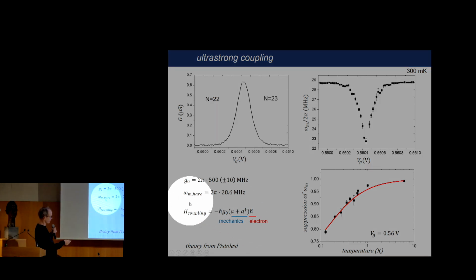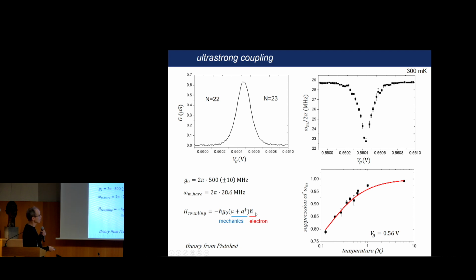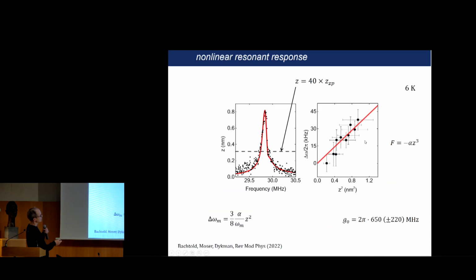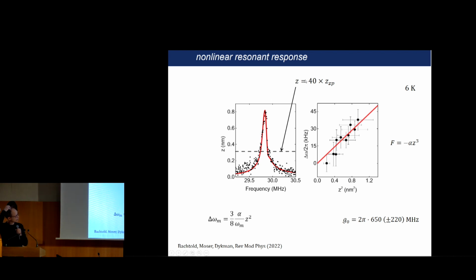And so here you can see the form of the Hamiltonian to describe the coupling. So this is the coupling strength, this is the displacement, and this is the charge operator. So this strong coupling makes this big suppression of the mechanical frequency, but it also leads to nonlinearities. And now here I show you the mechanical response of the oscillator to an oscillating force. And it's nonlinear because the peak is asymmetric. And here, the horizontal dashed line gives 40 times the zero-point motion. This shows that you have nonlinear vibrations rather close to the zero-point motion, much closer than what has been achieved before.